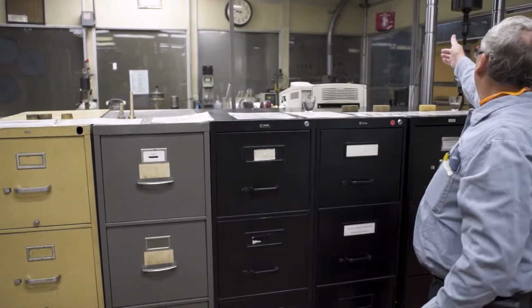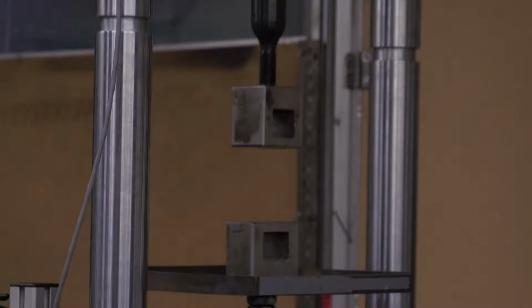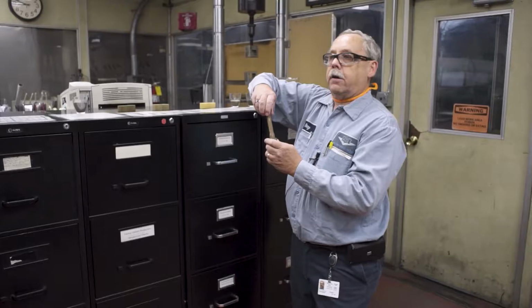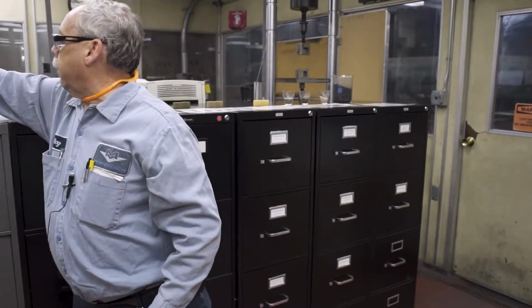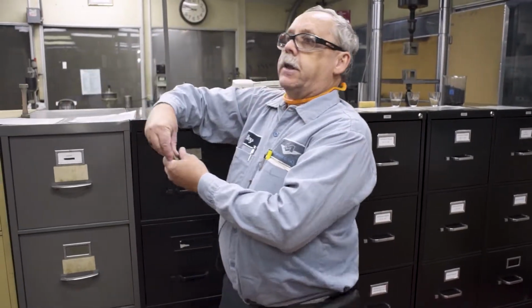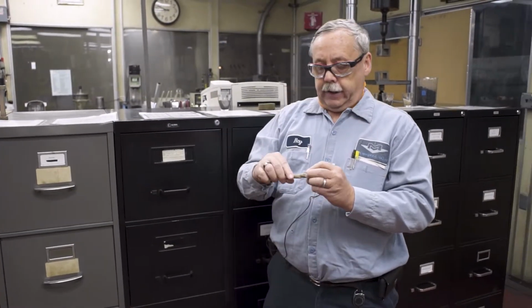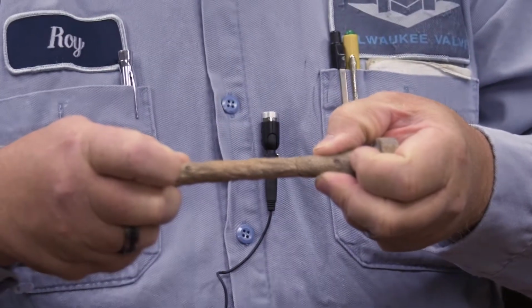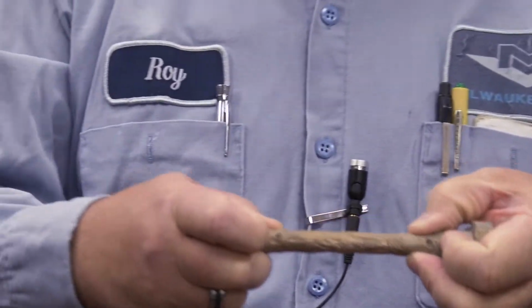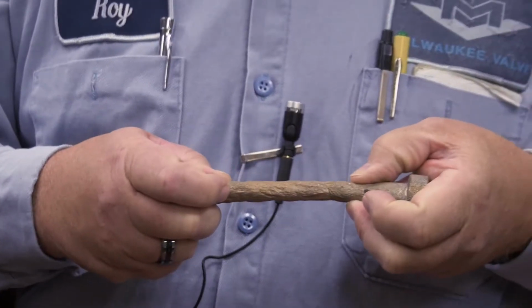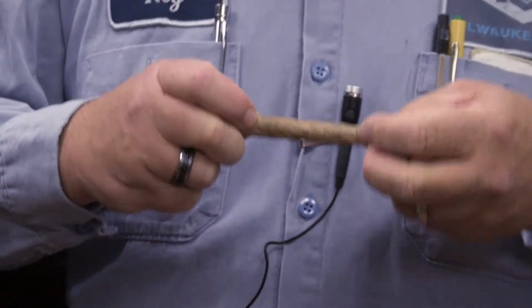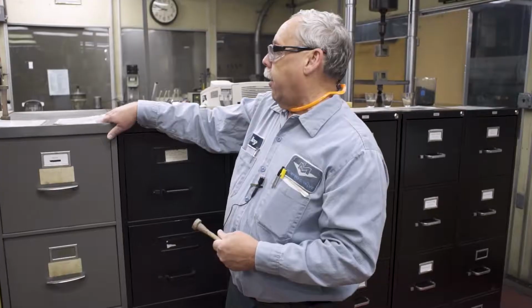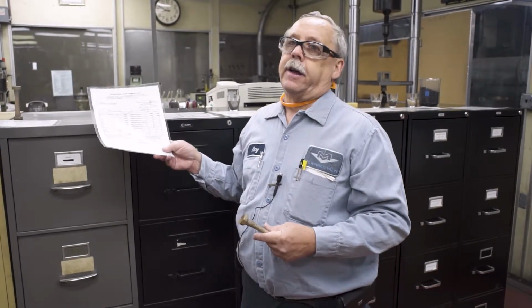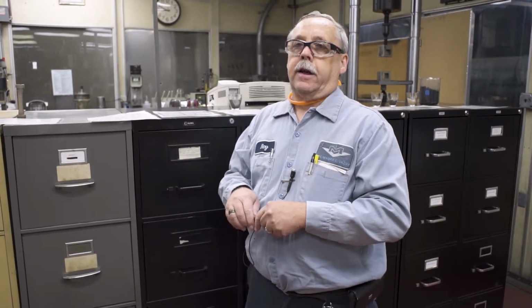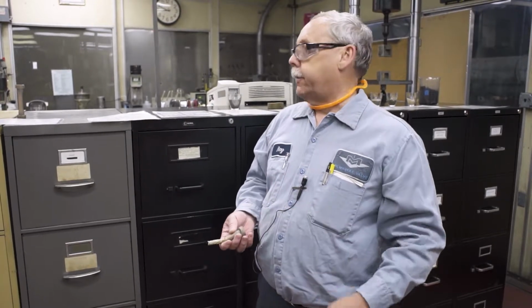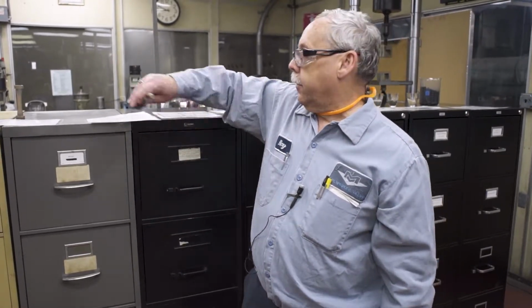We'll go and put a bar in a tensile bar tester here, pull the bar apart, and we get a yield strength, we get an ultimate tensile strength, and then we get an elongation. These points, we measure these points. They start out at 2 inches. There's a minimum elongation, there's a minimal yield, and a minimal tensile that we have to meet. And then the end record is also inputted into a form like this and kept again electronically in our system for each set of test bars that we do.